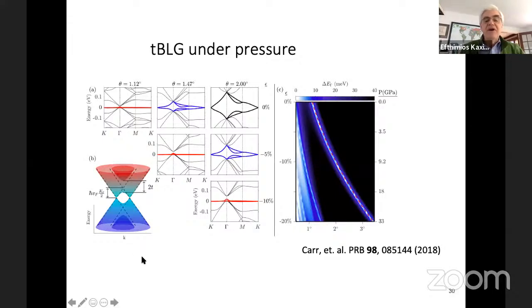So this is all very, very exciting, because the first thing that occurred to us, this is work by my student Stephen Carr and other members of my group, is that these are the flat bands that I showed you a moment ago, the highlighted flat bands at an angle of 1.12 degrees and zero pressure. But at a different angle, 1.47 degrees, the bands are not so flat. At 2 degrees, the bands are not flat at all. But if you apply pressure, because of the analysis of the relaxations that we did, you can make the bands flat again. Going down this axis, you compress the layers. This is 5% compression, which corresponds to a certain pressure. This is 10% compression. So you start with flat bands here. The bands at larger angles are not flat, but you can make them flat again. So this is the magic angle, the angle at which the bands become flat, and this changes as a function of the pressure. This is the pressure in gigapascals.